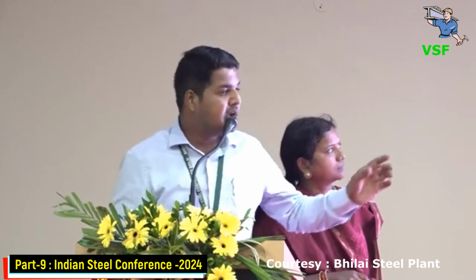This is the resilient modulus test results. Resilient modulus is a property of the material by which it takes the load and it defines its elastic limitations. This is the principle of the shakedown characteristics. We have tested the material, and according to its plastic deformation curve, where the performance or curve is changing, we have plotted a tangent and marked the positions. According to that we are marking range A, B and C.